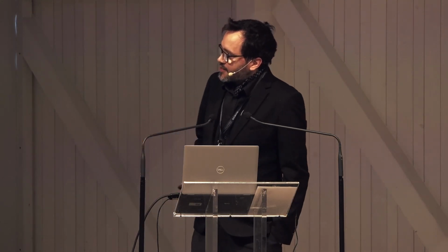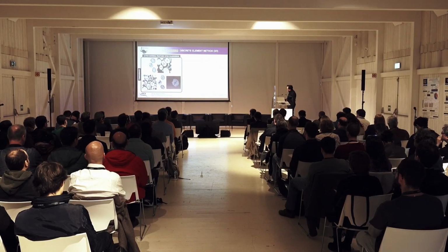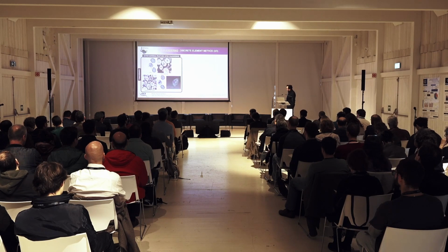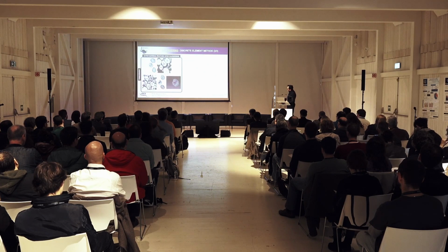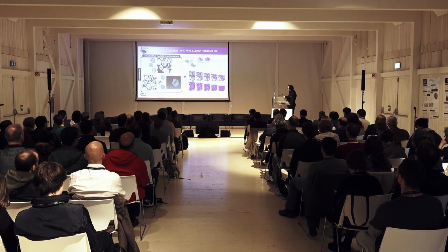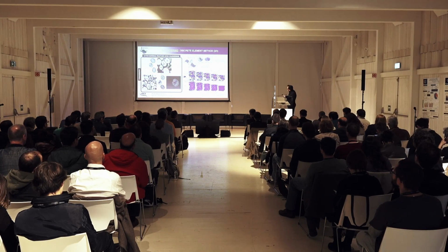You can also extend this model further and track, for instance, the cracking. Okay, this is something that we have done inspired by some nano computer tomography experiments that we have performed. where we observe that when you go very hard in terms of calendering conditions, when you apply very high pressures, the active material particles will start to crack. And this is something that you can capture in the model by extending this discrete element method by accounting for bond breaking phenomena. Basically, the active material particles are defined as a collection of spherical primary particles. Then we track the mechanical stress between these spherical primary particles as a function of the applied pressure upon calendering. And then we can visualize and see where the cracks are going to happen.